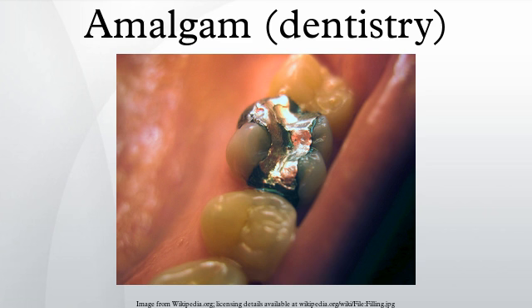The amalgam expands 0.1% over 6-8 hours by the slow aging reaction, 3 Ag3Sn + Hg → Ag2Hg3 + Sn7Hg. Non-metallic composite fillings are typically 1 to 5 µm silicate glass particles bonded by a UV-cured methacrylate resin. See also: dental composite, dentistry, mercury poisoning, references.